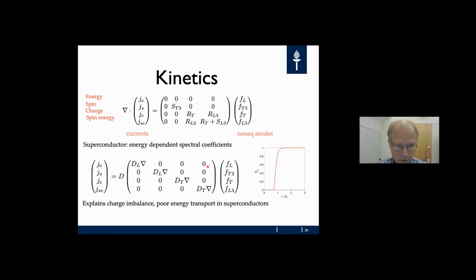If you study this in a superconductor, the first thing you get is that the spectral coefficients, called the diffusion, become energy dependent. You cannot do this energy integral trick anymore, so you have to do it energy resolved first. You get basically two spectral diffusion constants, dL and dt, describing separately energy and charge transport.